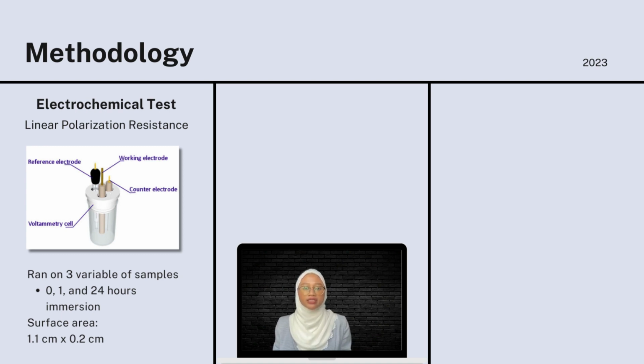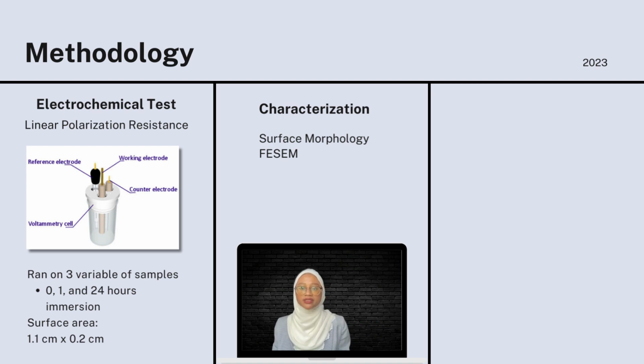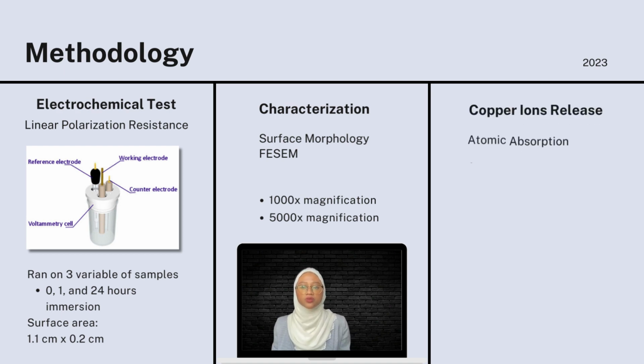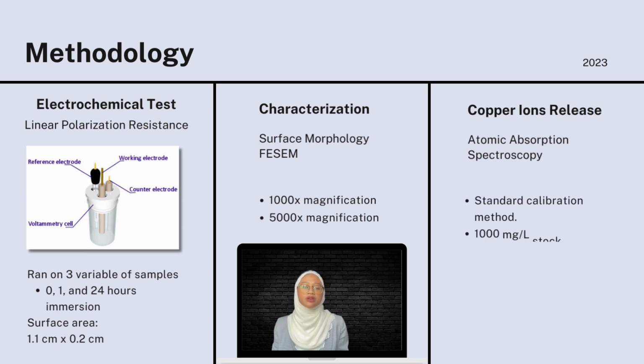All samples were then covered to limit the surface area to 0.22 cm squared only. Second part was the characterization of copper surface before and after the immersion using FESEM, which was done at 1000 times magnification and 5000 times magnification for better observation of the surface morphology. And lastly was quantifying the amount of copper ions released in the artificial sweat solution by standard calibration method of AAS.